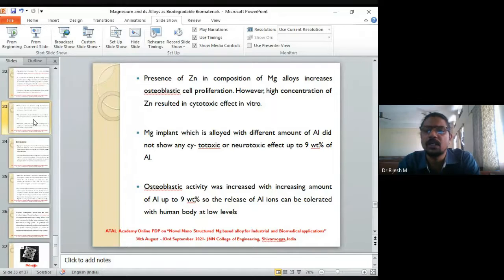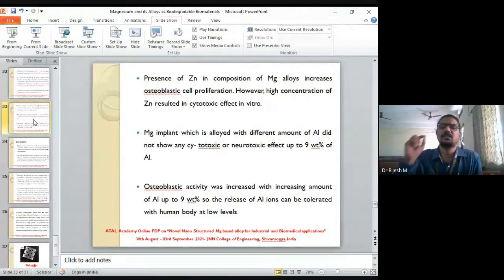But there is another issue here. Anything which crosses the limit becomes a problem. That becomes cytotoxic. So zinc in certain concentrations is good for this, but if the zinc is beyond that, you'll have a cytotoxic effect.